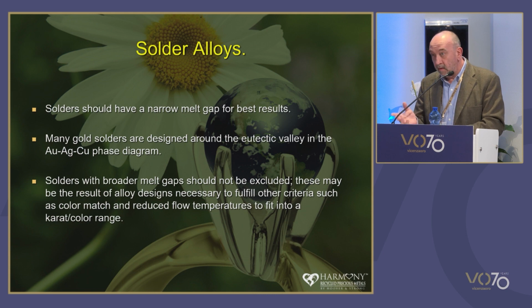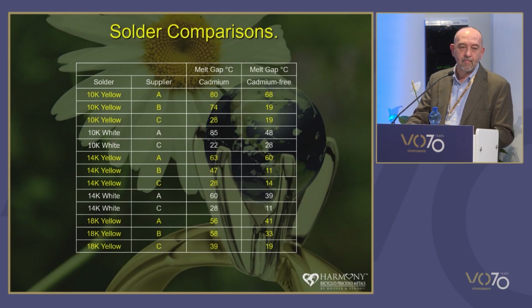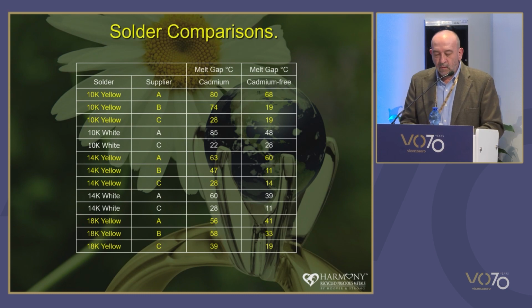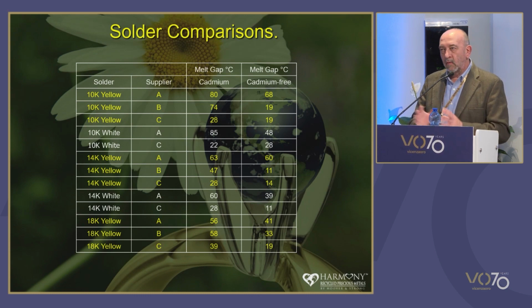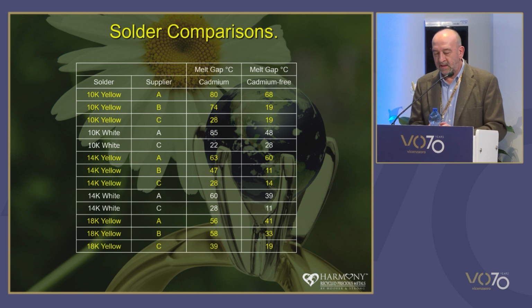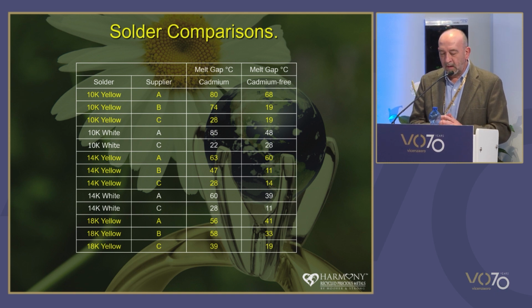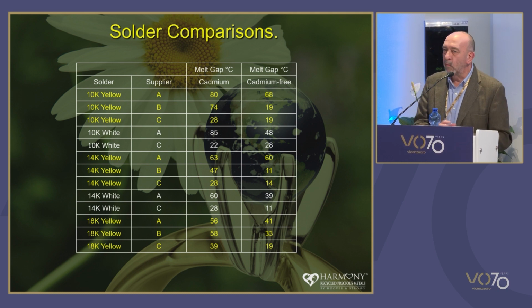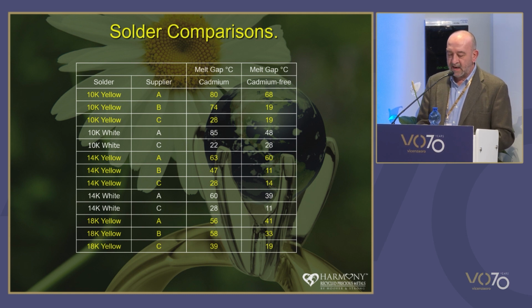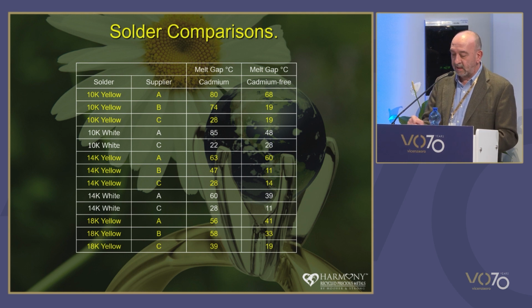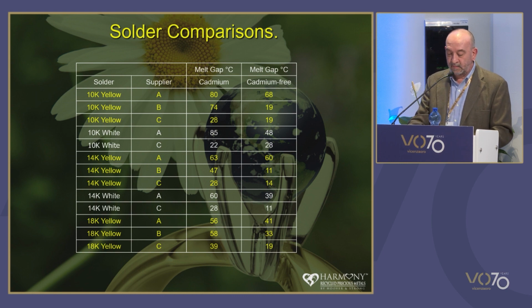So to start the project, we did a survey of solders and their published temperature data from 3 solder suppliers, one of them being the company I work for. And this is what we found. None of this data that a jeweler or a manufacturer gets is composition-based. It's just published data on melt gap, melt range, and whether or not it contains cadmium. Regardless of what else there is in there, all but one of the cadmium-free solders has a narrower melt gap than the cadmium-containing solders, which should be very beneficial when used in action.